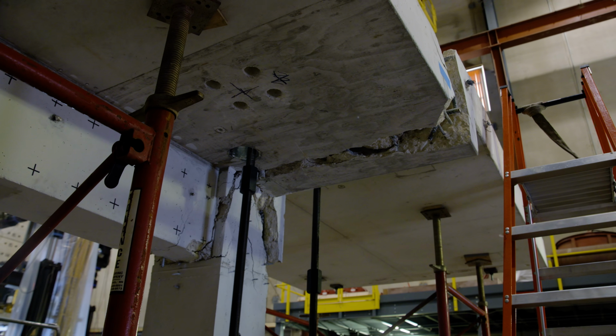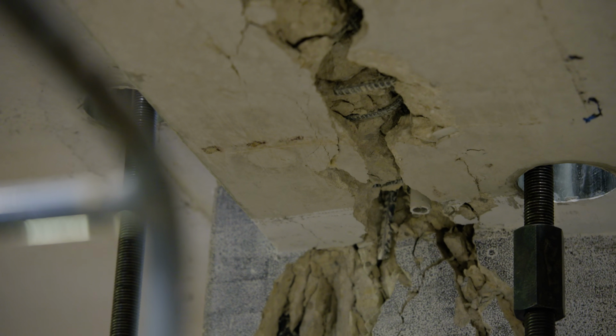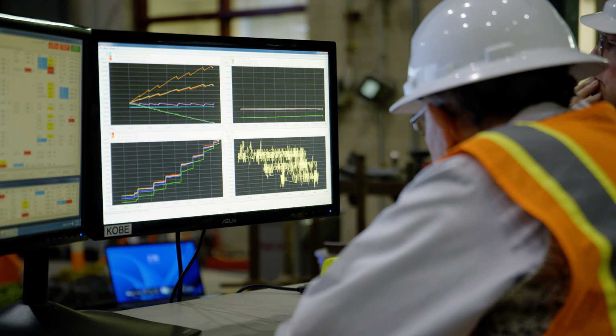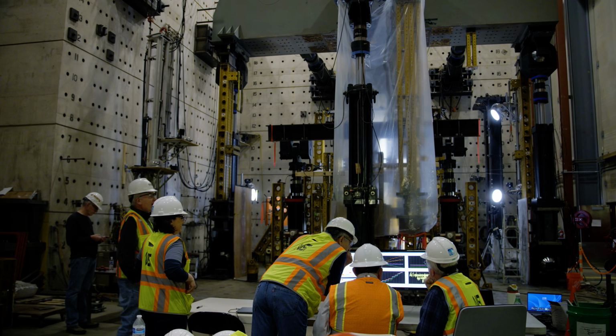Cement has a chemical identity, and that chemical identity is going to impact the susceptibility of any given concrete to environmental factors. Replicating the concrete is absolutely critical. We then realized that the kind of Portland cement powder that would have been available in the late 1970s was essentially no longer available. So the kind of cement that would have been used then was very, very hard to find. We found a place in South Florida that was still making the classic cement. So now we had the nearest approximation.